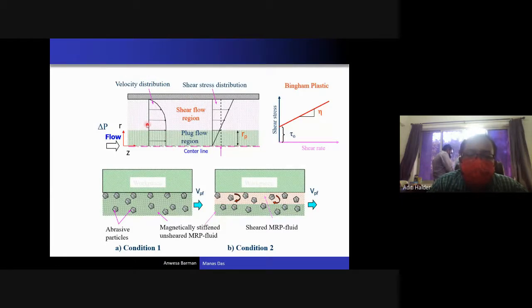If you see a normal Newtonian fluid, the flow profile is parabolic. But when you use this kind of non-Newtonian fluid, there are two zones. In the plug flow region, the velocity gradient with respect to the radial direction, del Vz by del R, is 0. So in this case the fluid chain structure does not break, as the shear stress is maximum at the wall and minimum at the center line. As the shear stress is maximum at the wall, the chain structure breaks at the wall itself.